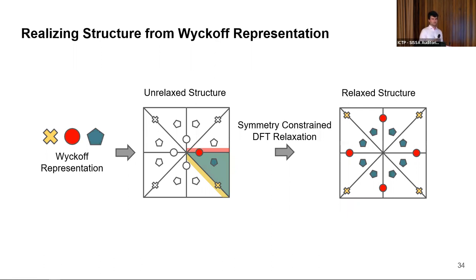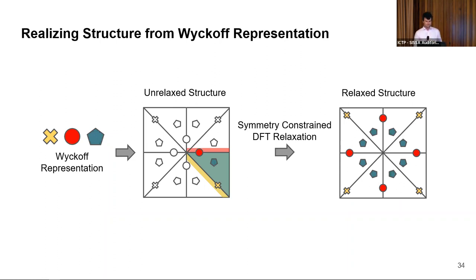These Wyckoff representations are passed into a graph attention network that updates embeddings for each atom based on all other atoms around it. This framework is called the Wyckoff Representation Network (WRN). It is used to predict the formation energy of the system. The key advantage is that you can easily reconstruct an unrelaxed crystal structure from this representation, it is completely enumerable for easy space search, and in most cases the representation is unique — edge cases of non-uniqueness occur only for very high-energy structures far above the convex hull.